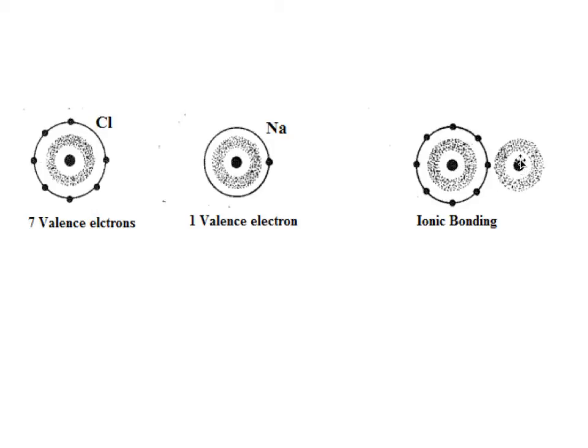The question is, what is this distance? Well, if you look closer at the inner shells, they have electrons, which of course are negatively charged, and if you push the atoms close together, these inner shells will overlap, and that means that we'll have repulsion forces between these inner shells. So we have attractive forces between the ions, but we have repulsion forces between the inner shells, and these two forces interact to give a certain atomic distance.